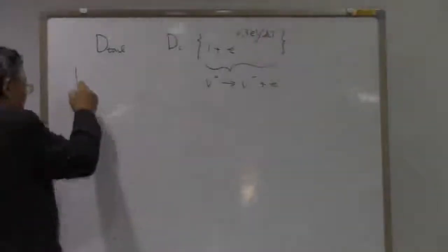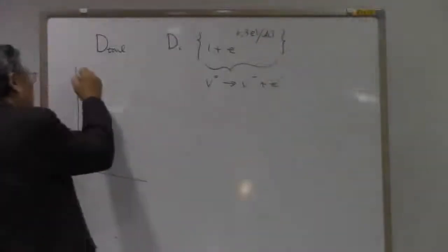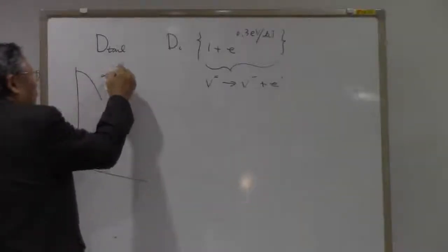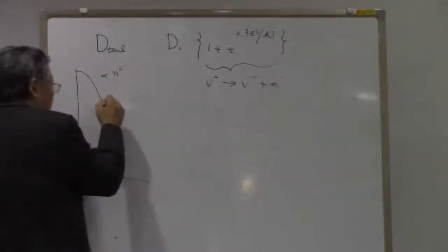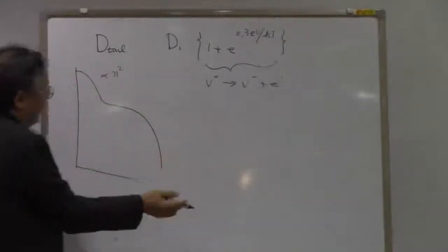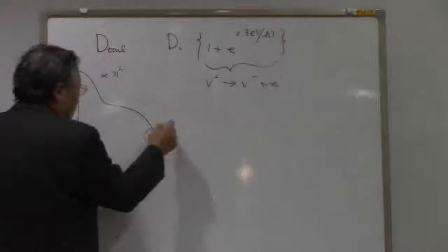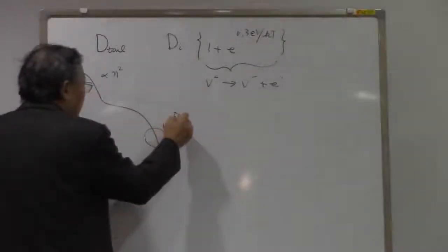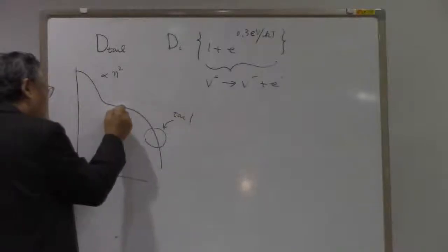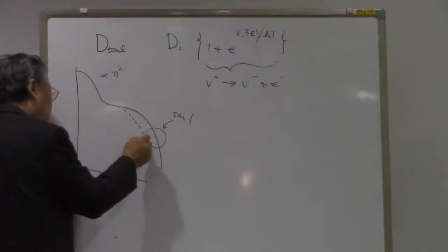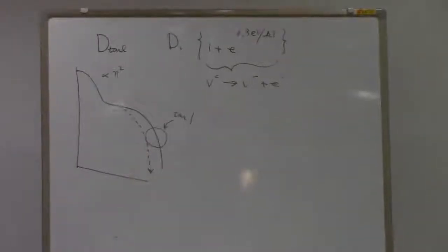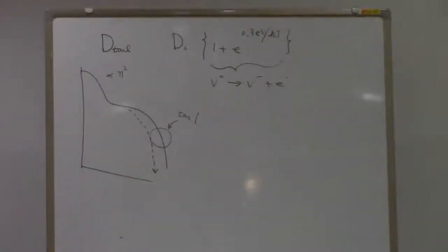So the profile we're going to have at the surface is proportional to n squared, and then with some enhancement at the tail. I just exaggerate a little bit. And in the tail region, we have some enhancement, something like this, when originally it should be something like this if we don't have any enhancement, right?